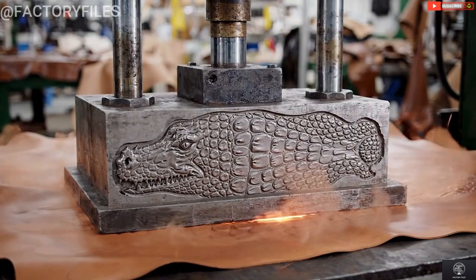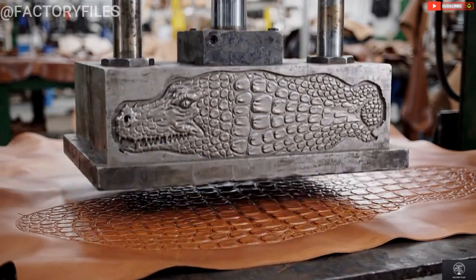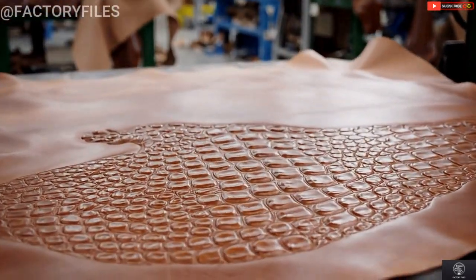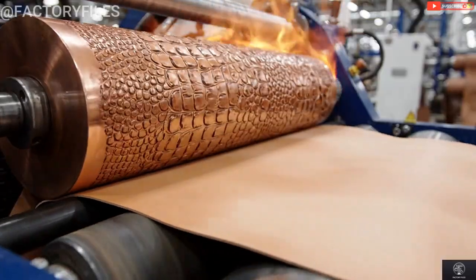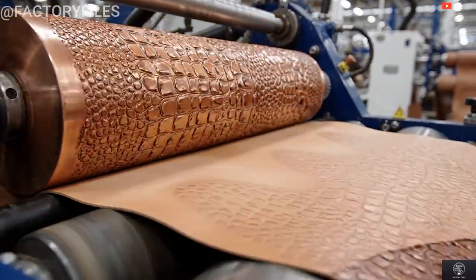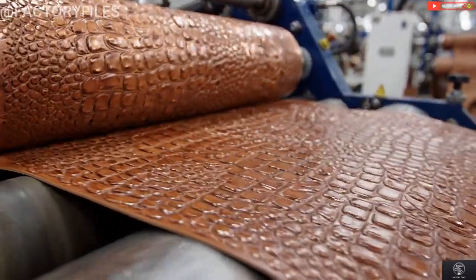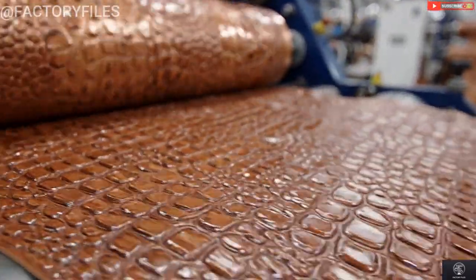The 50-ton press delivers its full force at 180 degrees Celsius for 3 seconds, permanently stamping the reverse pattern. For continuous production runs, a rotary embossing system uses an etched heated copper cylinder rotating against a backing roller.